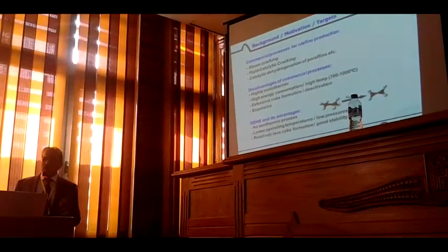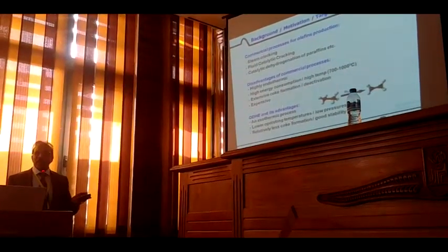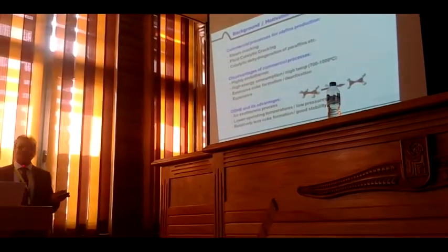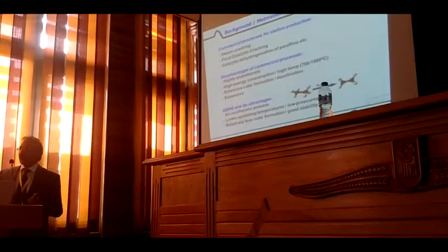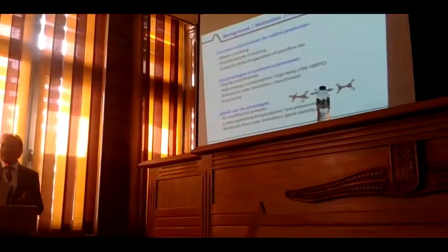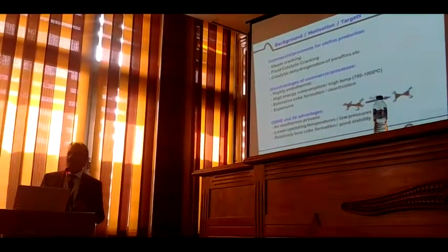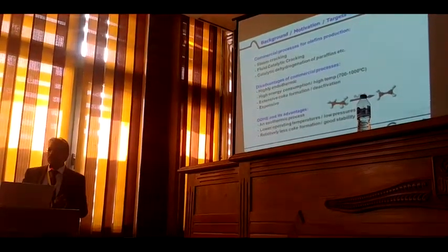So one good option is to introduce a little oxygen in your reactant feed and to dehydrogenate. This is called oxidative dehydrogenation, which is an exothermic process and operates at low temperatures. When it operates at low temperatures and you have the presence of oxygen, the paraffin, your alkane, will be easily activated at low temperatures. And the presence of oxygen will also burn the coke which is deposited there, so that it will enhance the long-term stability. But this approach is still at a developmental stage. It has not been commercialized yet. It might take another decade or so.